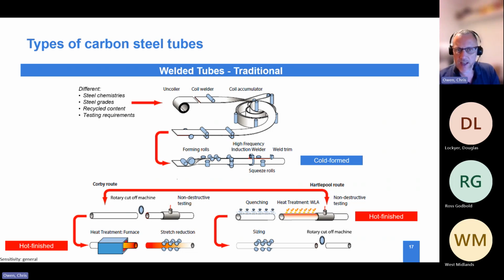And again, different testing requirements, not just on the tube, but the actual feedstock material. The coil undergoes quite a lot of testing and validation even before it gets into our tube manufacturing process. And you can see from the schematic that we're taking that coil, we weld the nose to the tail of the previous coil for a continuous process, and we're forming it into a tube profile, which then goes through that high frequency induction welder, and we cause the free ends to superheat, we squeeze it together. So that is basically a cold form tube.